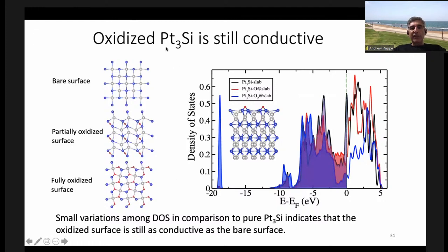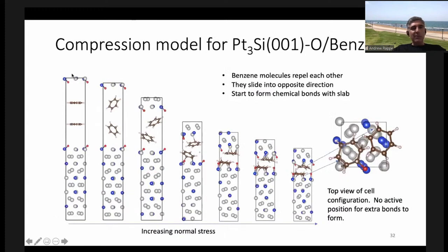So we first check, and by the way, this partially oxidized platinum silicide is still conductive. So it would still be fine for doing the tapping and closing the circuit. And then we apply this methodology now for the third time, compressing the solid and allowing that to transfer stress to the molecules. So again, they tilt, but then under pressure, the tilting is squeezed out.